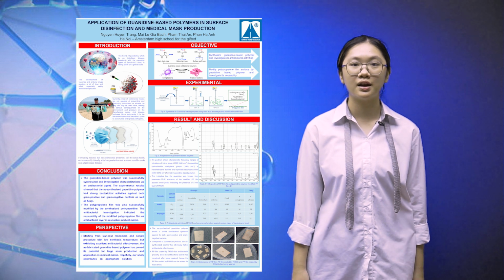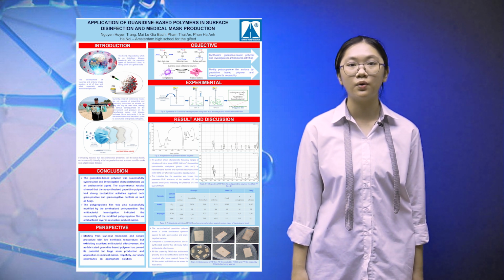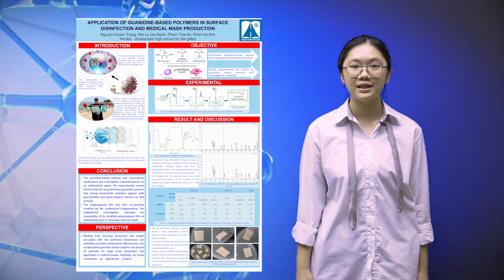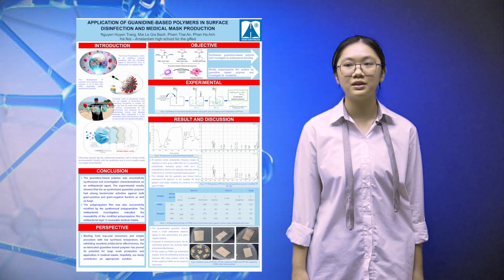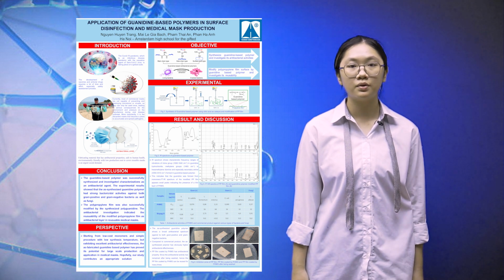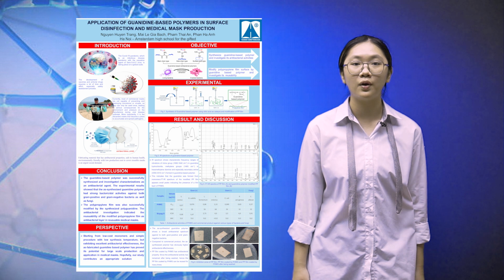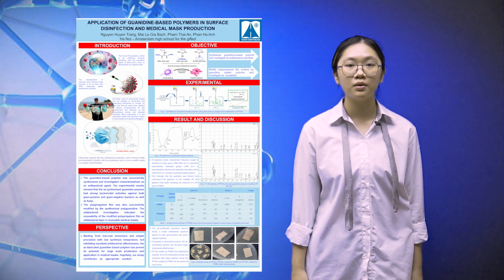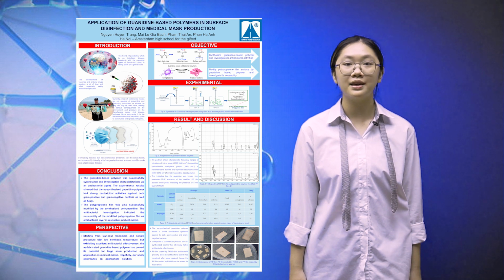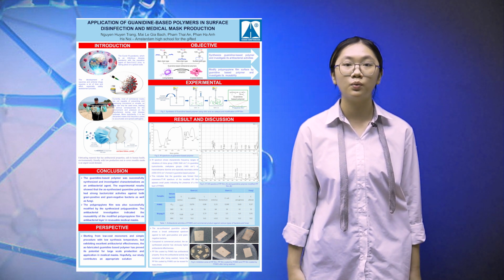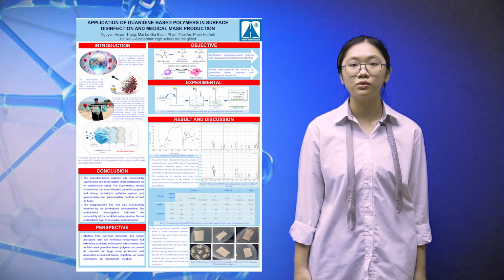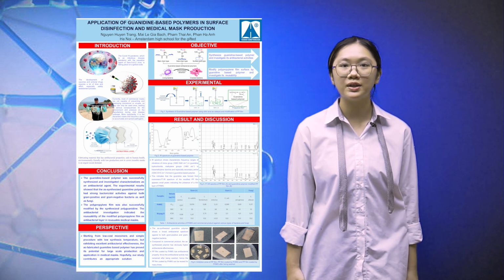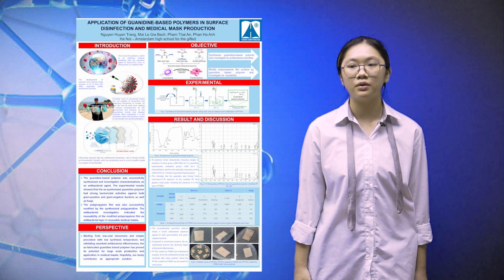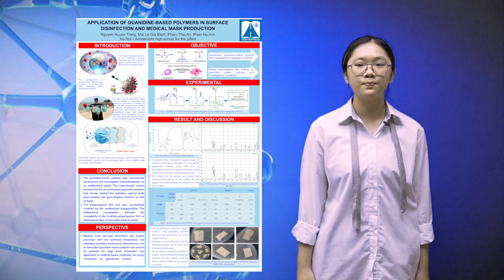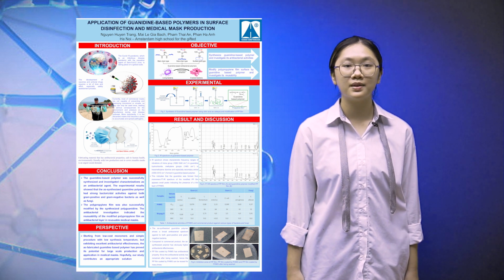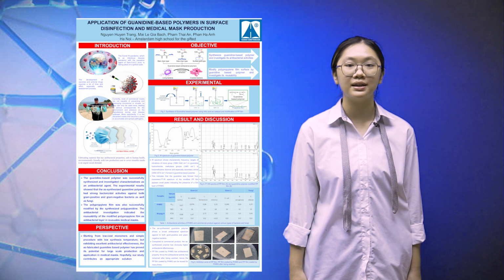These peaks, with frequencies at 2934, 2860, and 1464 wave number, are responsible for the CH bond stretching and bending vibration in the methylene group. Another peak at 1644 wave number represents the C=N bond vibration from guanidine hydrochloride, indicating that both monomers are well incorporated in the final product. The IR spectrum shows the absence of a peak at 3500 wave number, which represents the primary amino group, but instead a broad, strong peak at 3326 and 3180 wave number, which represents the secondary amine. This proves PHMG is successfully synthesized from the reaction between hexamethylene diamine and guanidine hydrochloride.